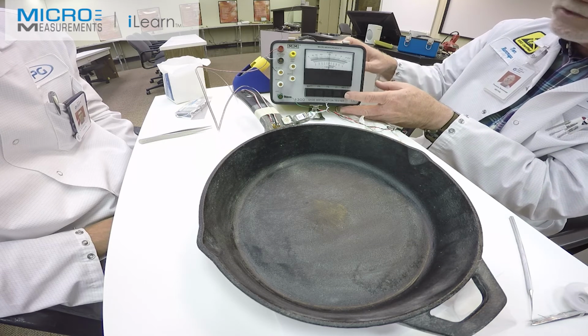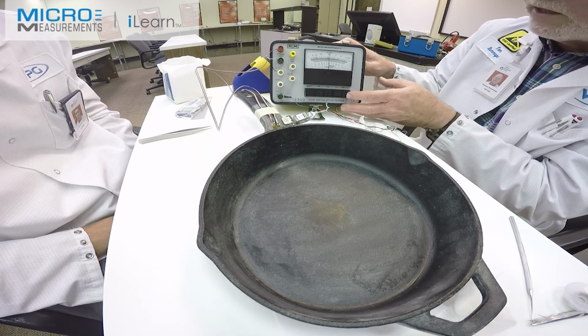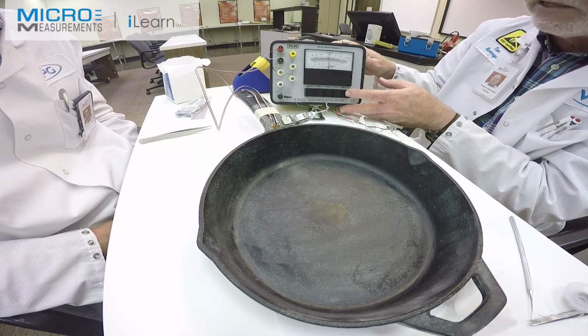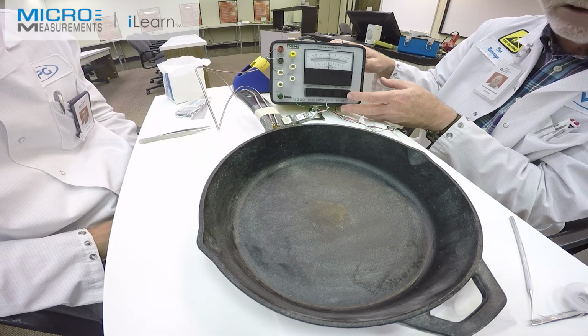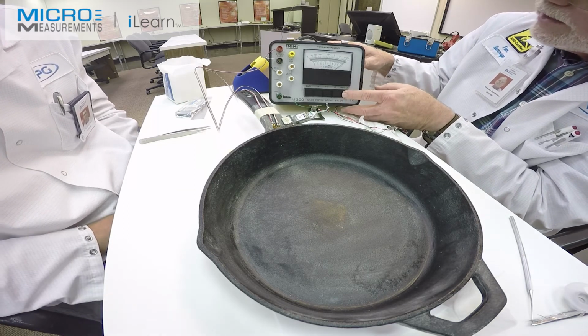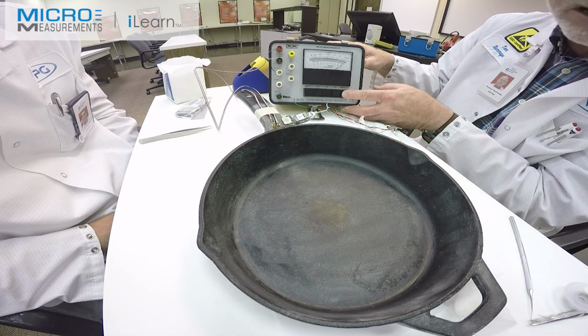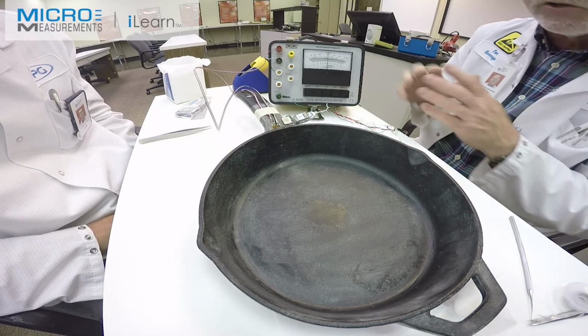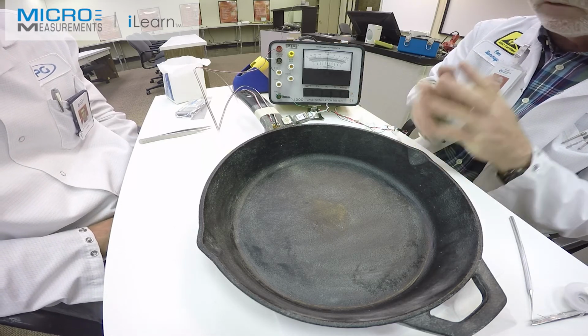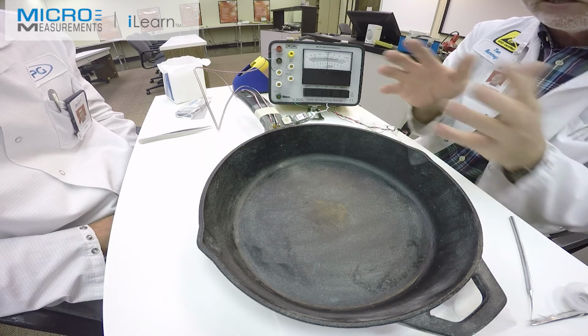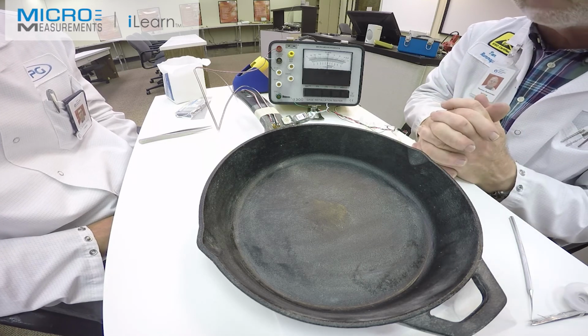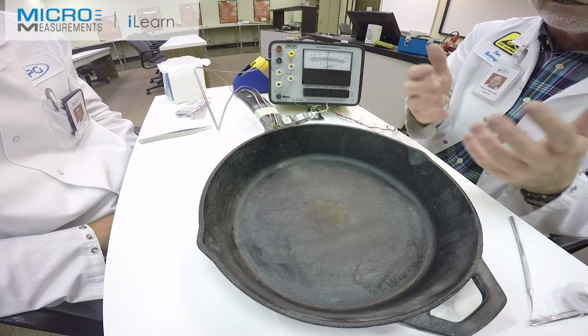That is the megohms resistance, and in a properly installed strain gauge it should be at least 10K megohms resistance to ground or better. And in this case, it's riding up near infinity, so we've done a fairly good job of cleaning up the flux, and we've checked out electrically. We have not checked out the gauge mechanically. You can only do that by loading the part.